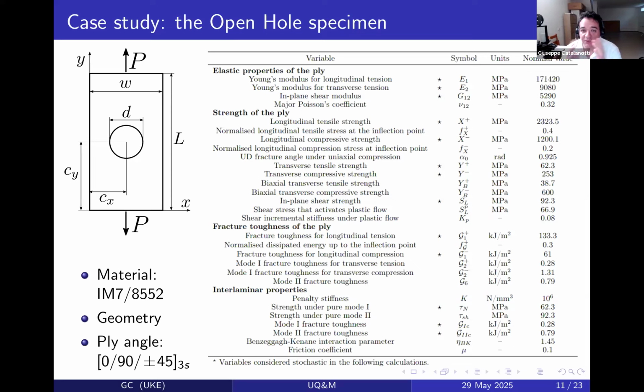Okay, so let's assume, for example, the parameters that are considered in the model to be stochastic, but there is no limitation. You can assume everything to be stochastic, are the material parameters that are highlighted with a star. Also, you have geometrical parameters, right? And the ply angle. So the geometry is highlighted there. So the length of the specimen, Cx and Cy, that are the position of the hole, the diameter of the hole, the width of the specimen, and also the ply angle.